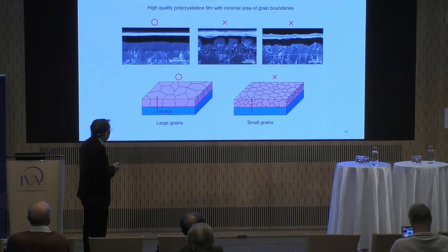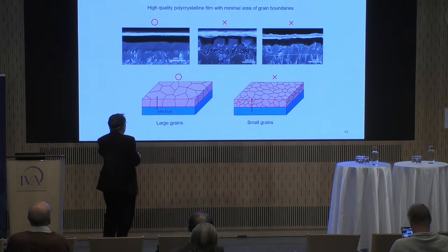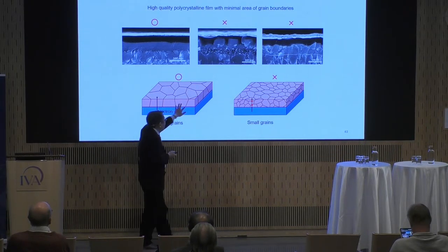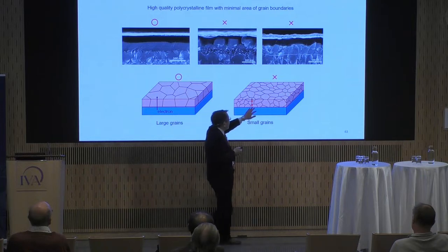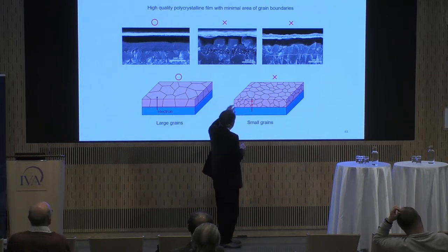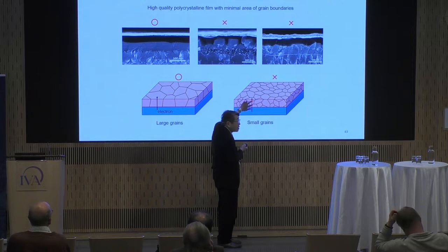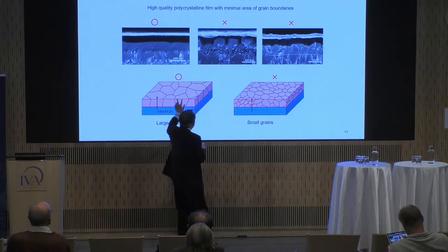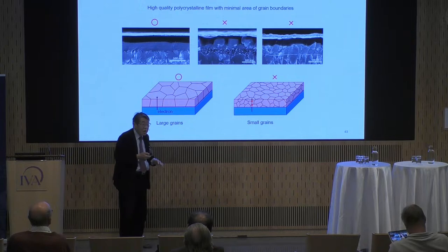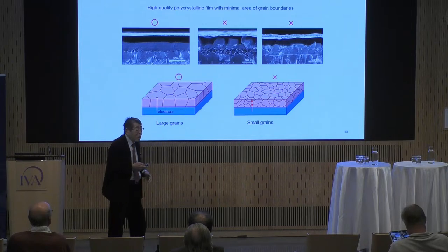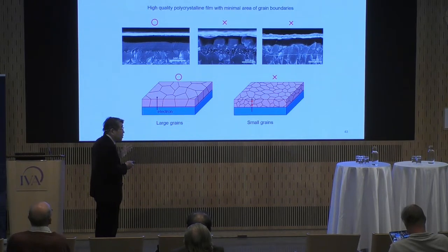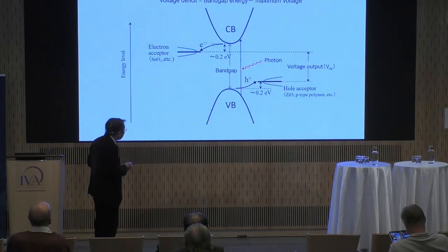But engineering is very difficult. Just by evaporating solvent, we have to make a highly packed, large grain polycrystalline layer. If we cannot make a large grain, the grain boundary area is rich in defects. So we'd like to make this kind of layer. How can we make this kind of layer just by coating the solvent? This is a very high tech technique for the makers, the companies.